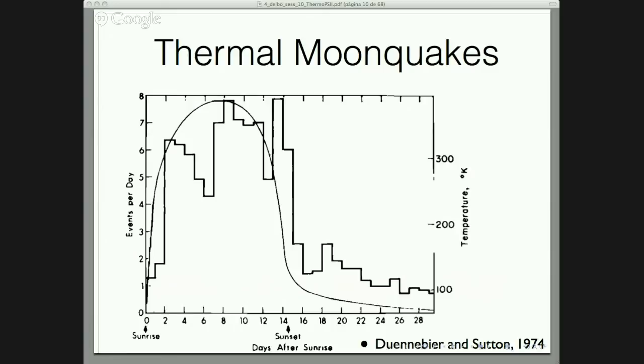And here you see, from this paper by Duennebier and Sutton in '74, the histogram of events measured by the Apollo seismic network deployed on the Moon as a function of days after sunrise. You see there's a very good correlation between these little events. It could be cracking of rocks on the Moon, or landslides, but there's a very good correlation with the diurnal cycle. So the interpretation is that it's probably due to some thermal events.